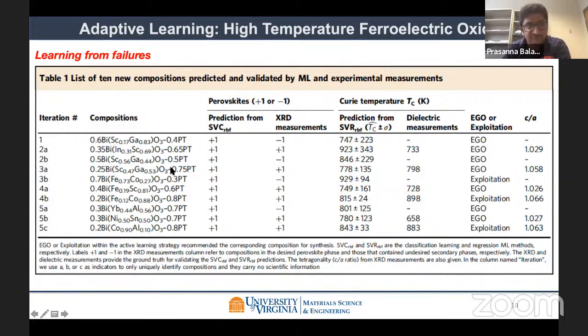But then in the third iteration, we were able to see a plus and a plus. So adaptively the model was learning, even from failed data, and adjusting the decision boundary so that at the end of the day we were able to identify the composition we want with the desired structure and property. We did five iterations, and they led to 10 new compositions. If you follow the pluses and minuses here, six of them agreed with experiments. There were four disagreements, which led to improvement. So we were able to leverage even the failed results.